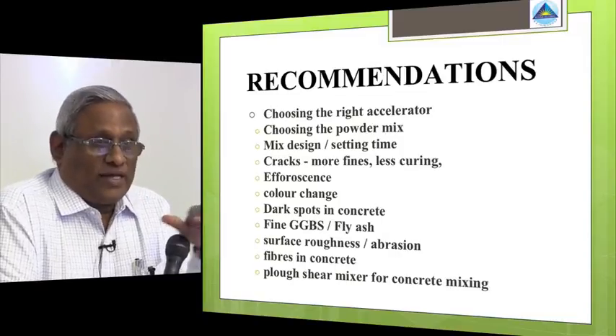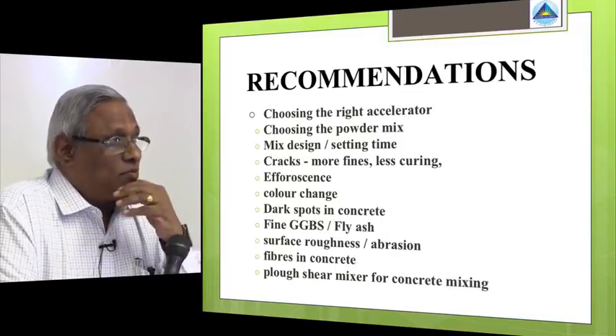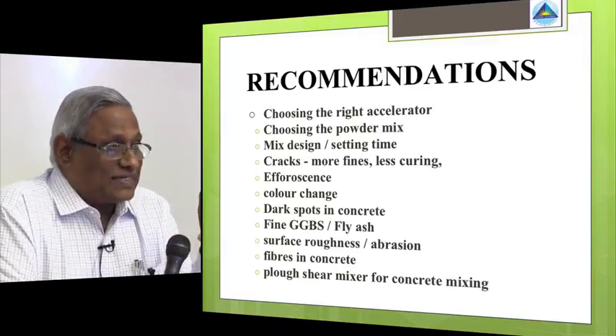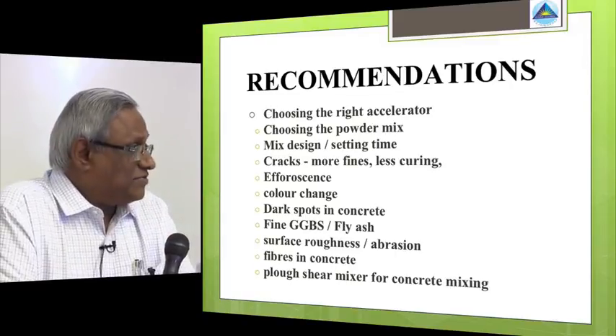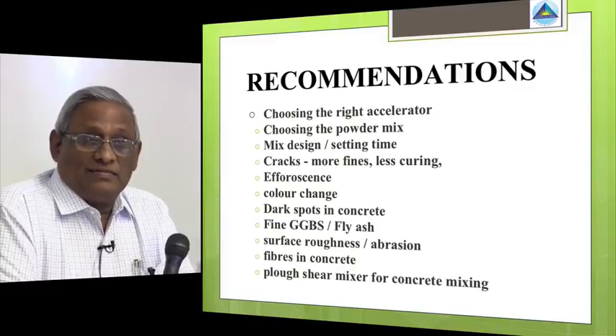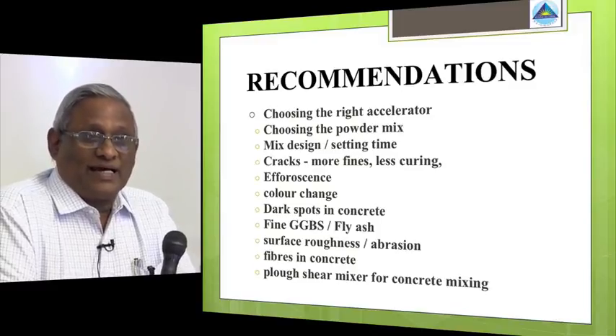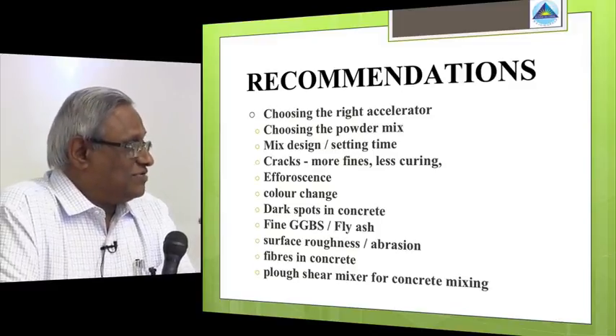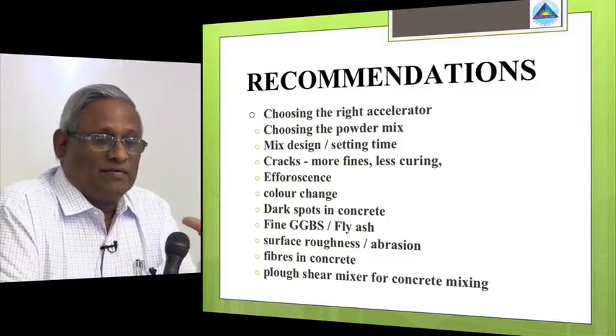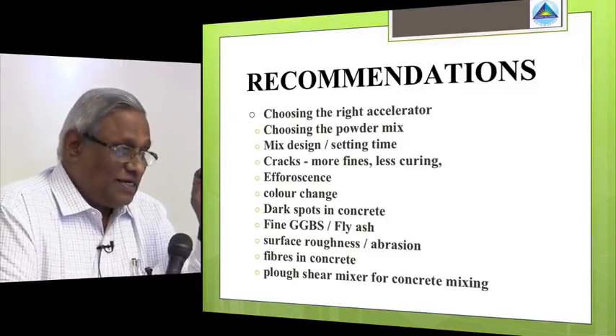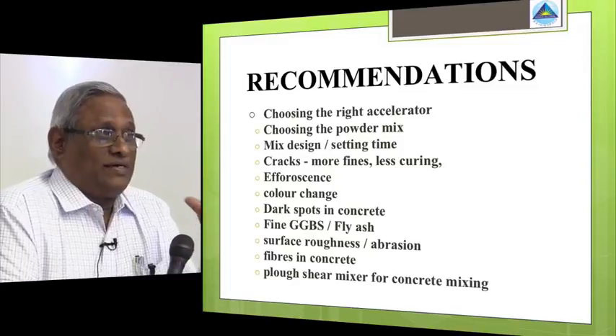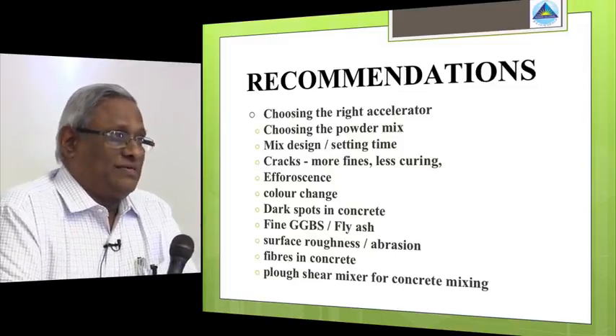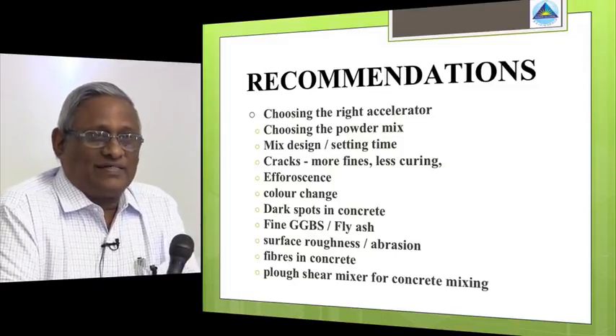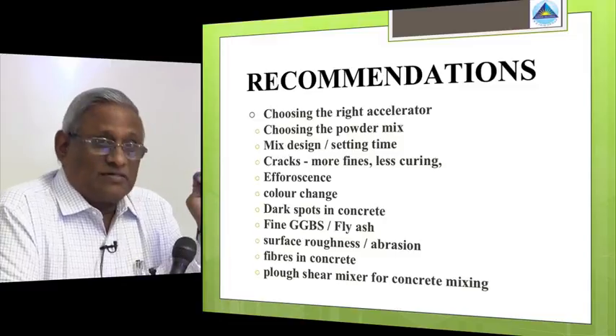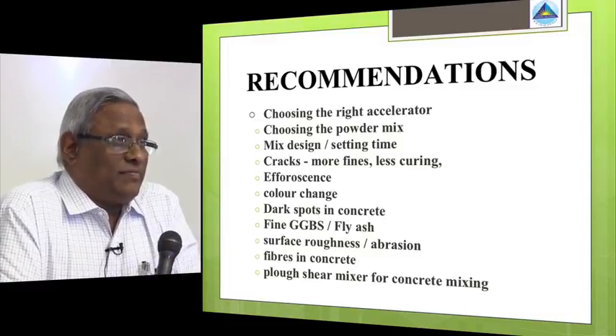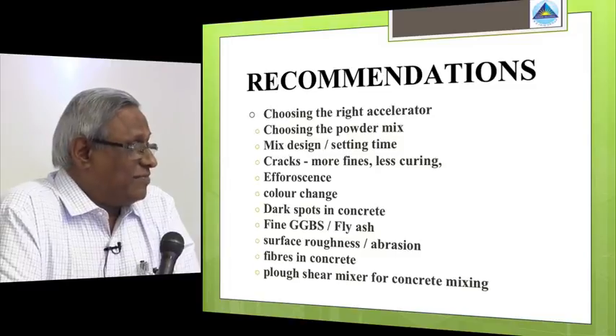In case when we are doing some of the precast block pavers, we do a two-layer casting. We lay a top layer casting which is very hard, and we use a bottom layer casting which is normal, so that the top surface is always maintained abrasion resistant. Another advantage of doing the two layers is the top layer can be colored, pigmented. You can create designs.